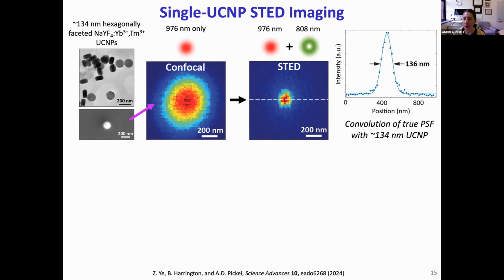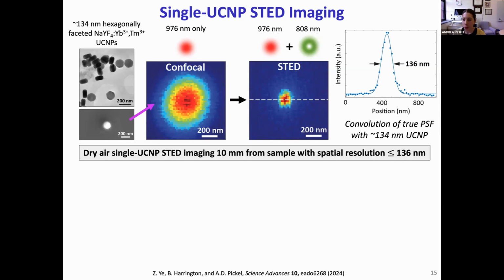And I'll emphasize that these images are a convolution of our true imaging point spread function with the UCNP. So because we're able to image right down to the UCNP size, that suggests that our true spatial resolution is almost certainly better than 136 nanometers. And so again, that means that what we've shown is the ability to do dry air single UCNP STED imaging with our objective 10 millimeters away from the sample, while simultaneously resolving orders of magnitude smaller than that working distance.